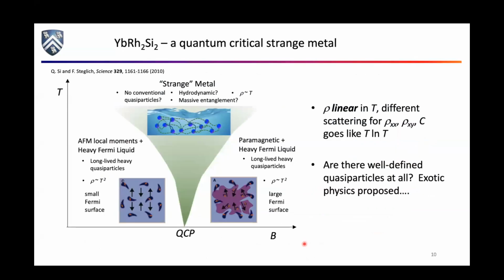The example we choose to work with is ytterbium-rhodium-2-silicon-2. This is a material that's been well known for 20 years, if not more. The basic idea with this material, if you go down towards absolute zero, there's a quantum critical point between an antiferromagnetic state, where the ytterbium atoms order, the f electrons order antiferromagnetically, and you have a small Fermi surface. Quasiparticles are kind of heavyish.